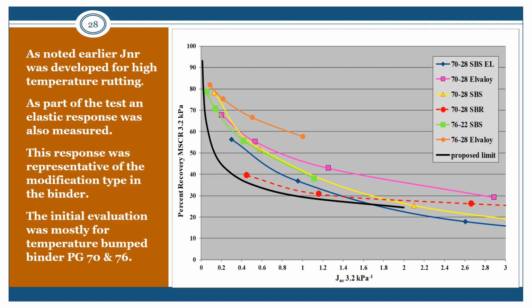So let's look at some of the issues and properties of the M332 specification. When we originally developed the specification, we looked at a lot of existing binders, and we tested them at multiple temperatures to see what they looked like and what the relationship was in the MSCR specification as compared to the M320 specification. And so you can see here several 70-28 binders made with different formulations, and a couple of different PG 76 grade binders, again with 2 different modifications. Now, just to have a little bit better way of looking at this, we want to show you this exact same data.